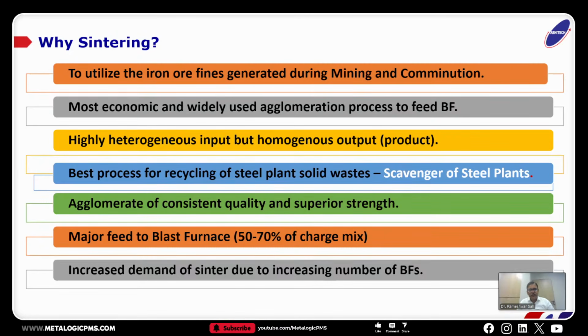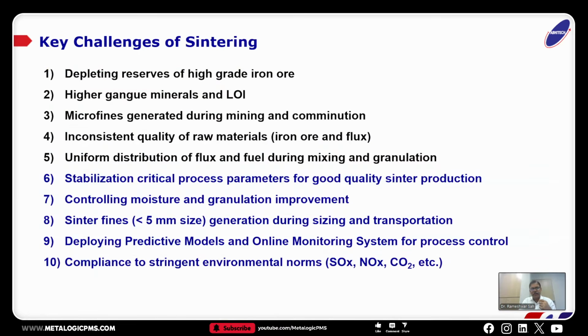What we see is that in the major blast furnace feed all over, either India or abroad, sinter accounts for almost 50 to 70% of the iron ore charge mix in the furnaces. That's why the whole functioning of the blast furnace becomes very smooth if we have very good quality sinters. So there is going to be an increasing demand for sinters, because of the capacity expansion of steel in India, more and more blast furnaces are coming. Most of the expansion is through the BF-BOF route, and that requires a very high demand for sinters.